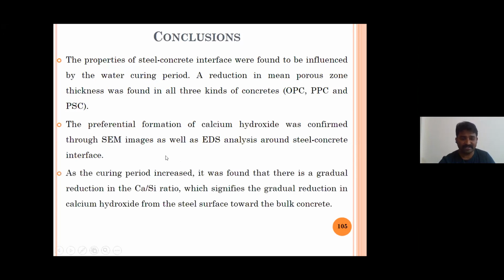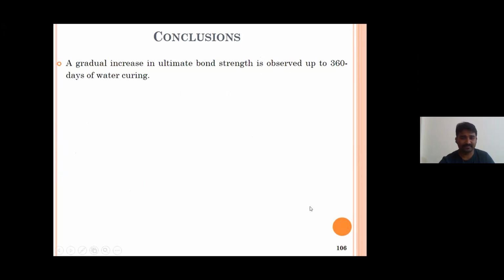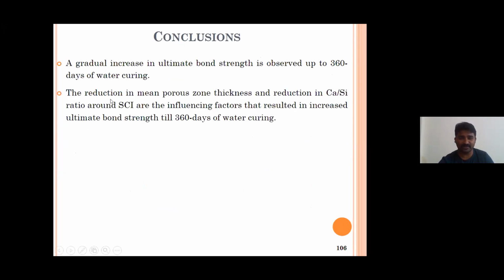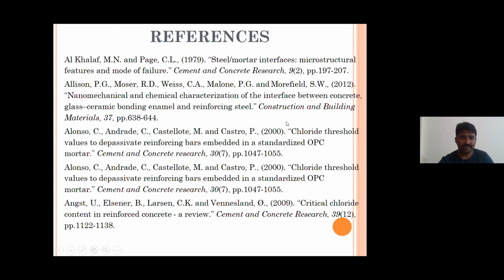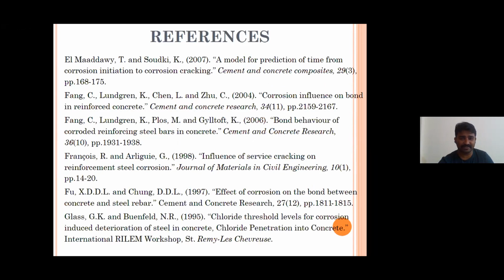As curing period increased, it was found that there is a gradual reduction in Ca/Si ratio, which signifies a gradual reduction in calcium hydroxide from the steel surface towards the bulk concrete. A gradual increase in ultimate bond strength is observed up to 360 days because of water curing. That contributes to a reduction in mean porous zone thickness as well as a reduction in Ca/Si ratios at the steel-concrete interface. So these were a few of the references that I have selected.